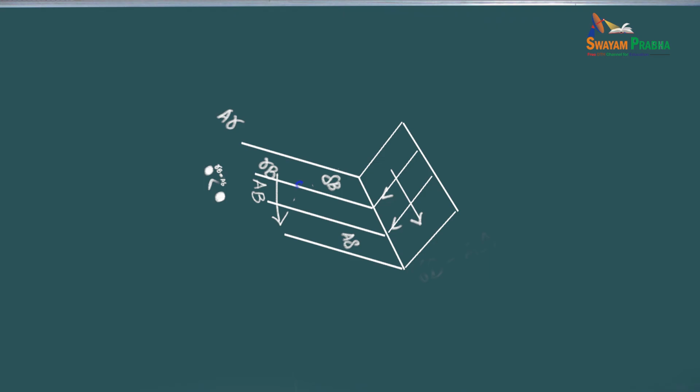And the bottom face here is this plane here. It's not really cross-slip. It's a dislocation that lives in two 111 planes. It forms, for example, as a result of a junction formation and breaking. You can see many of them. We'll show you examples afterwards. It's a dislocation that lives in two different 111 planes.